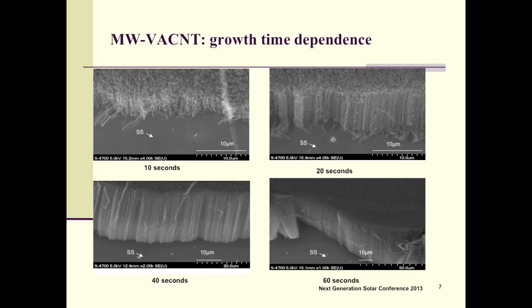So these are the SEM images. These are the side views. We have grown these carbon nanotubes with different time exposures: 10 seconds, 20 seconds, 40 seconds, and 60 seconds. We characterized them, growth rate versus length, and we found that for the 10-second growth, the length is about 5 microns, and then 10 microns, 20 microns, and 60 microns respectively. For this particular system, we found the growth rate is 0.5 to 1 micron per second, and we can grow carbon nanotubes using this method up to millimeters.